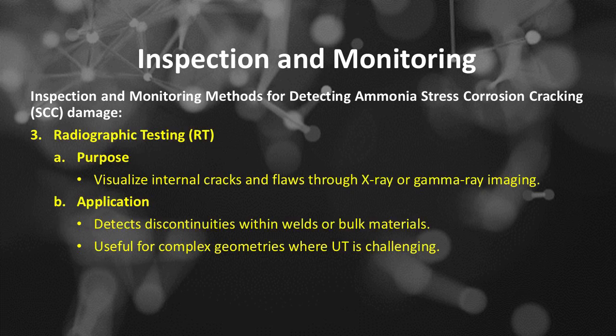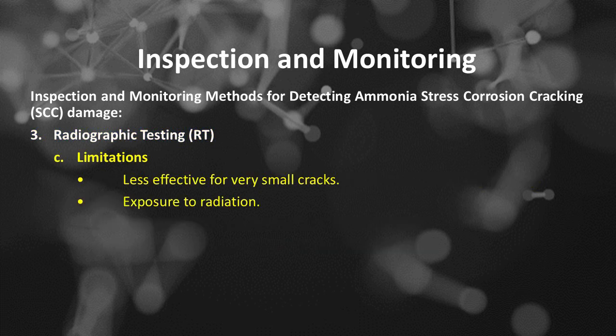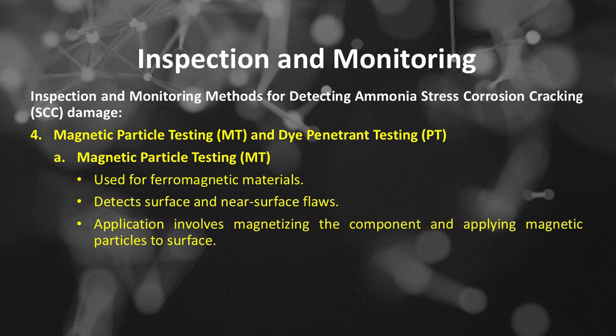Number 3 of inspection and monitoring methods for detecting ammonia stress corrosion cracking damage is radiographic testing, or RT. This RT is purposed to visualize internal cracks and flaws through X-ray or gamma-ray imaging. RT is applied to detect discontinuities within welds or bulk materials. RT is useful for complex geometries where UT is challenging. Radiographic testing limitations: RT is less effective for very small cracks, and there is RT exposure to radiation.